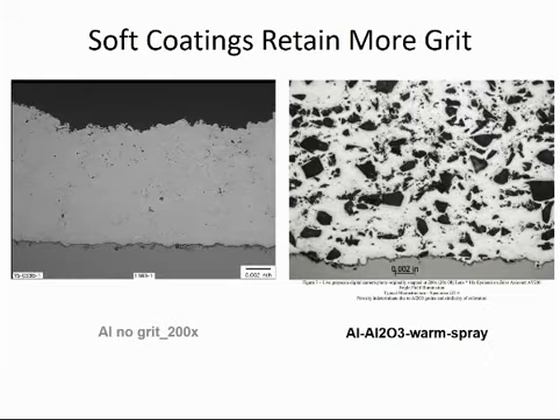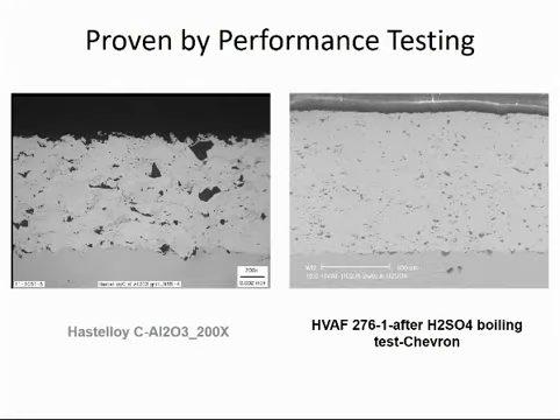Here we have a soft coating example. This is aluminum sprayed with no grit, and it's a respectable coating as aluminum goes, nothing really terrible. But with grit, a lot more is retained in the coating, clearly metal matrix. It's impossible to tell what the porosity is because of the aluminum oxide, but once again, our gas permeability tester allows us to see that this coating is superior to that one. Amazing. Who would have thought?